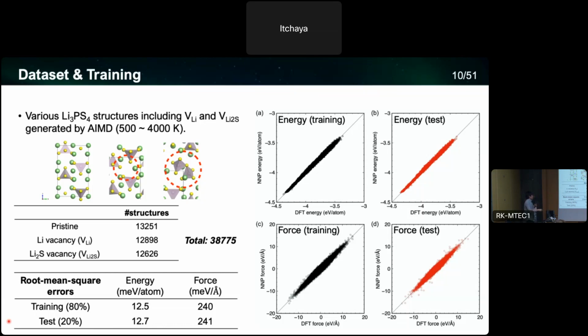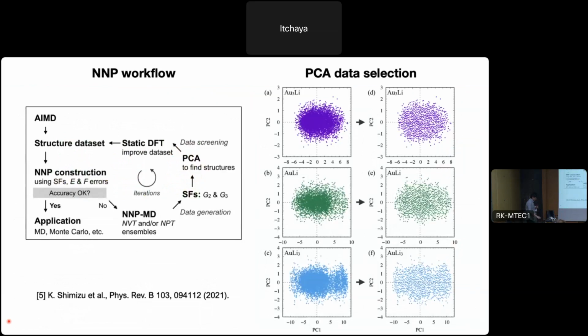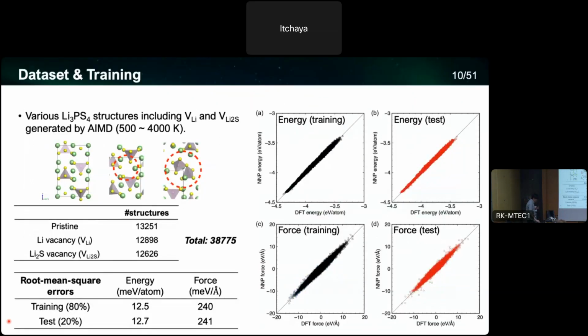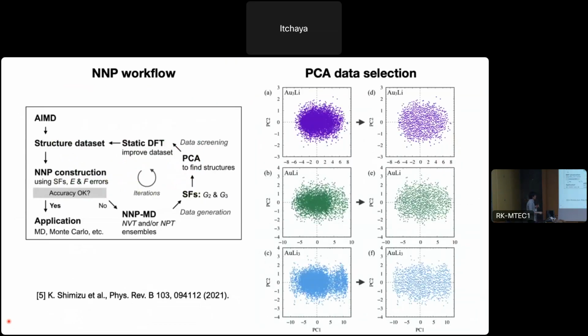Well, if you are familiar with machine learning potentials, these values are not very good. But as we can see, all the data points are located on the diagonal line, which indicates the training went very well. So we proceed to the molecular dynamics simulations using the constructed potential. But in the course of making these structures, we used some techniques proposed in this paper.